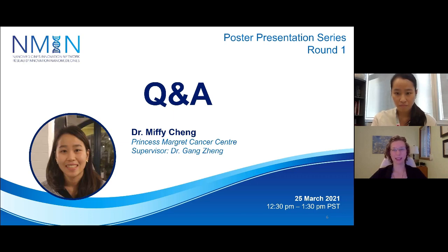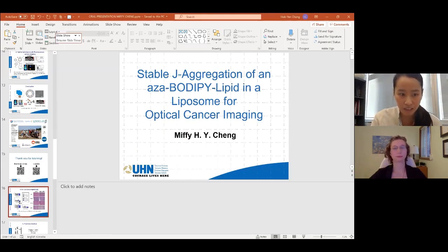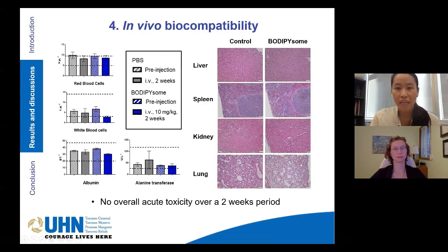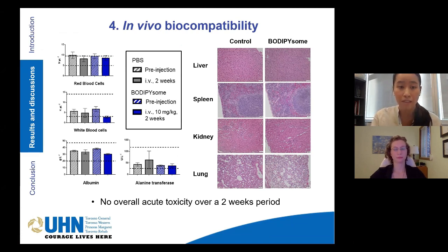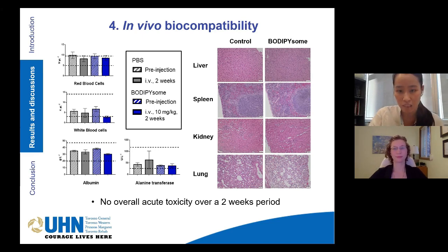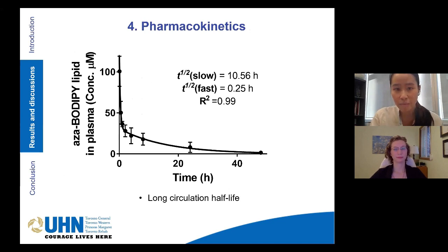Q: Did you do any exploration into pharmacokinetics or acute toxicity of this lipid? Yes, we did. We definitely did some acute toxicity studies because it is important that the liposomes remain safe and non-toxic. We performed blood count and liver function tests, and found no acute toxicity over a two-week period in mice injected with a higher dose of these BODIPYsomes. We also did histology to show there were no adverse effects observed in those histology slices. We also looked into pharmacokinetics, and found that the BODIPYsome has a relatively long circulating half-life of around almost 11 hours.